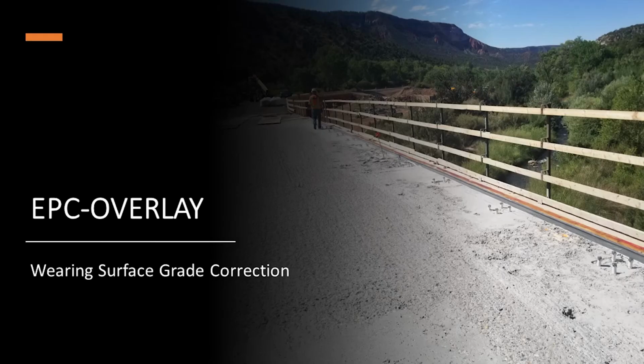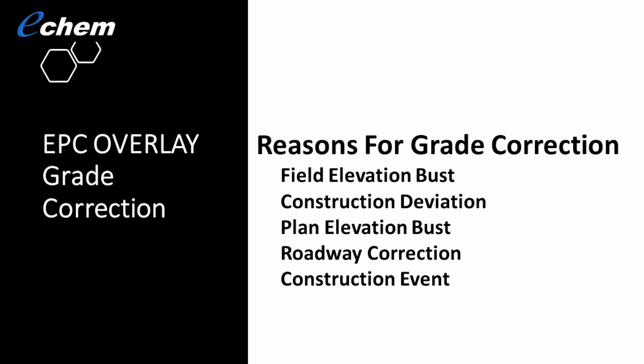This is the structure here that, just prior to pouring it, when we came in there, they actually did a heat map. We quantified the material, took down the high spots to reduce the material load on the structure. Reasons for grade correction are numerous, so it can be a field elevation bust, construction deviation, plan elevation bust, roadway correction, or a construction event like what happened on this project.